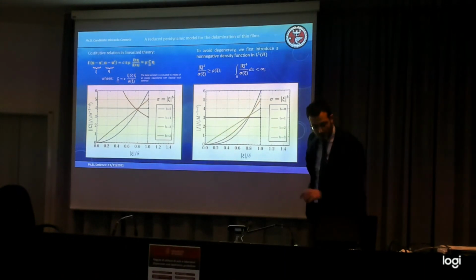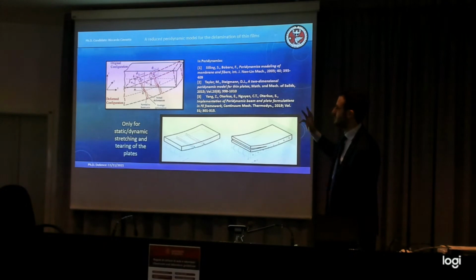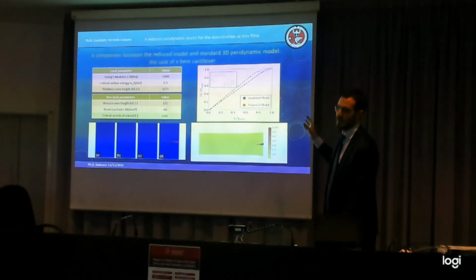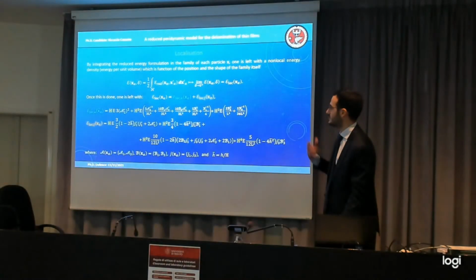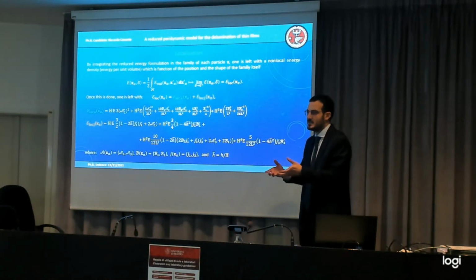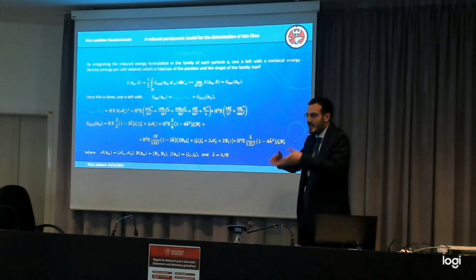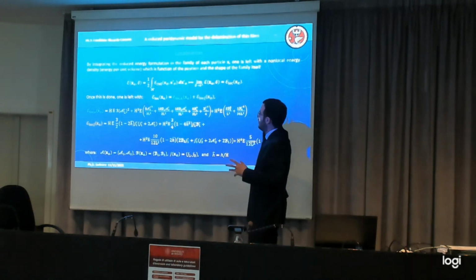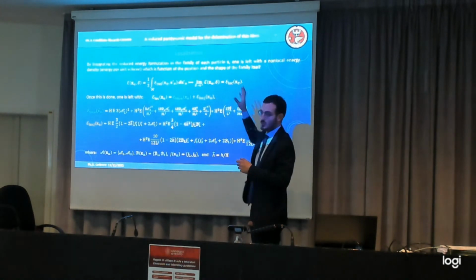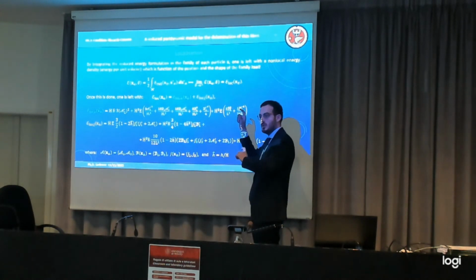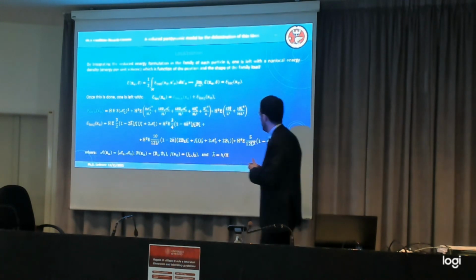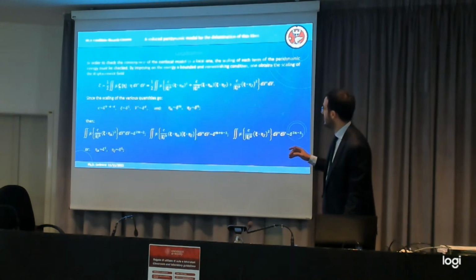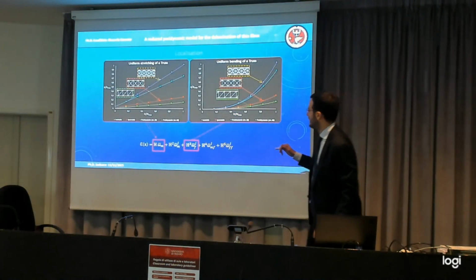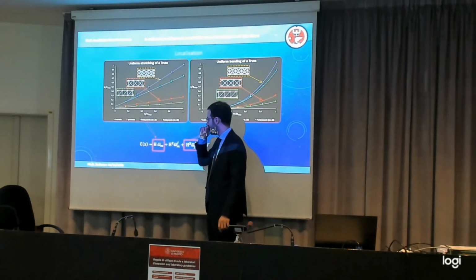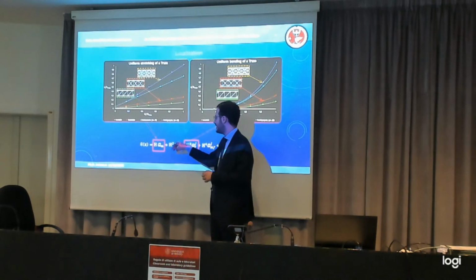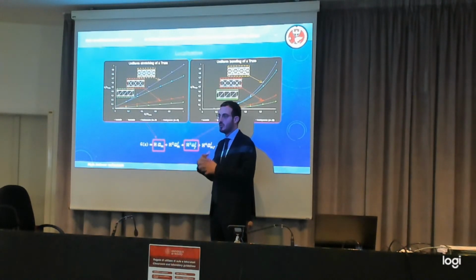Yes, we have seen that by localizing the model, it's more natural to talk about the localized model. It's more intuitive, and we have done it for many years. So at the beginning, we struggled with the non-local plane. We were talking with Luca, what is a non-local plane? How can I imagine it forming a non-local plane? So this is why we insisted so much in developing its localized equivalent in order to understand it better. And when we localized it, we saw that the energy was being absorbed by the model, even if there is a jump. And this is some kind of cohesive behavior.